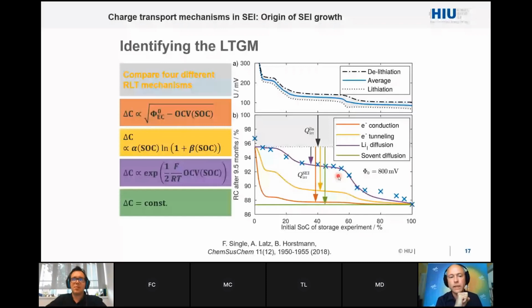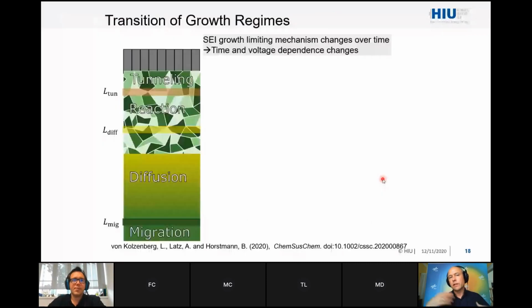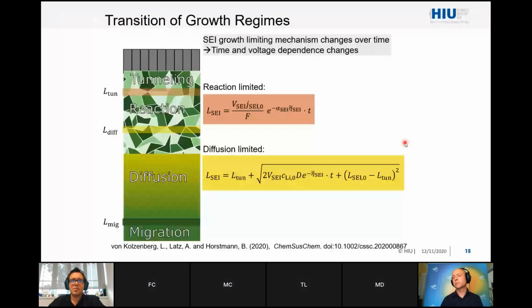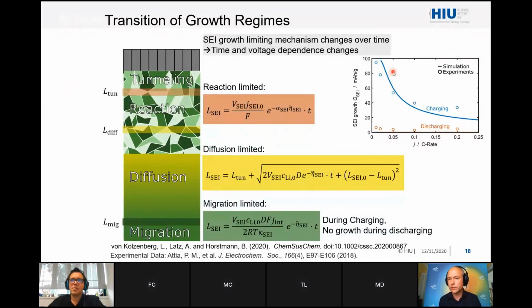exactly the observed behavior. The reason is that we have this exponential behavior where the OCV, so the potential difference between the electrolyte and the electrode, is entering. This strong dependence on the overpotential is responsible for a stepwise decay, and this is exactly the layered shape of the staging behavior of graphite during discharge or charge. We transformed this into a model for not only calendar aging but also for cycling. And we found that if we include this interstitial-mediated transport, we can recover the asymmetry of SEI growth during charging and discharge.